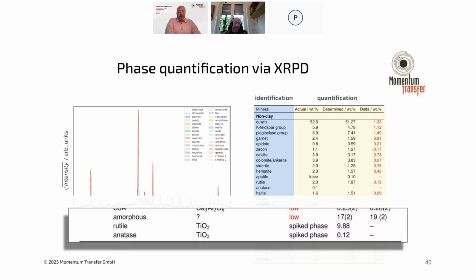Semi-quantitative analysis, you can actually directly use the relative scalings of all of these different phase contributions in your sample to estimate the phase fractions in your material. So if you don't have a significant amount of amorphous material present, a few percent or less, then these will already directly be representative of the phase concentrations or mineral concentrations in your sample.